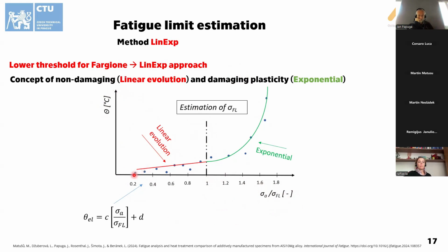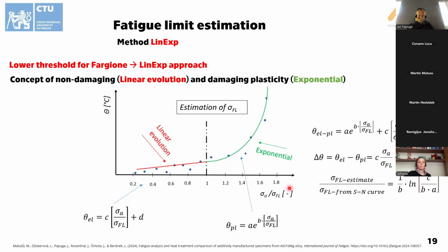But the first part is described as a stabilized temperature related to the elastic deformation, although I agree that there is microplasticization around the grains under the fatigue limit. I am aware of that. And the second part we described as a stabilized temperature related to the plastic deformation. And combining these two descriptions, we have the whole line, as you can see here.